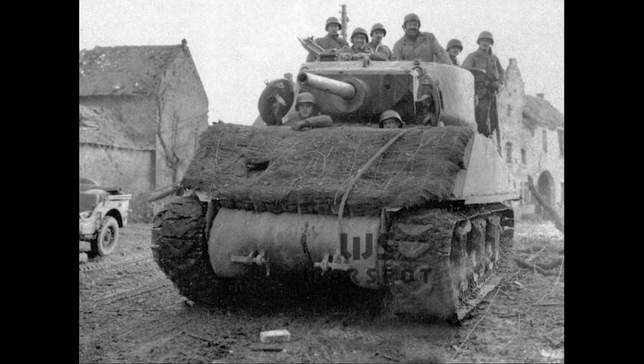8 times, 88mm shells struck the jumbo. The crew, unable to move, could only wait and hope the armour held. 7 of the shots ricocheted or failed to penetrate. The armour, even under concentrated fire from one of Germany's most powerful anti-tank weapons, performed as designed. But the 8th shot found a weakness. It struck just above the side sponson, slightly above the tracks, where the side armour was thinner and the angle less favourable. The shell penetrated.